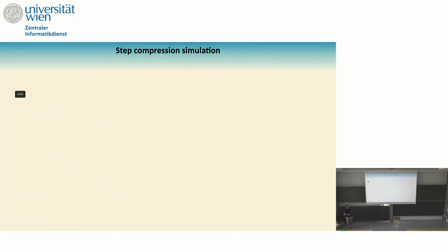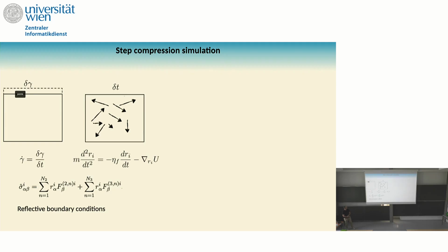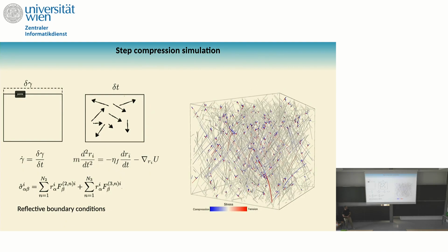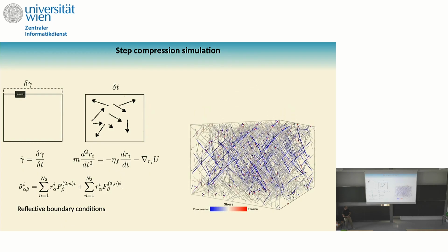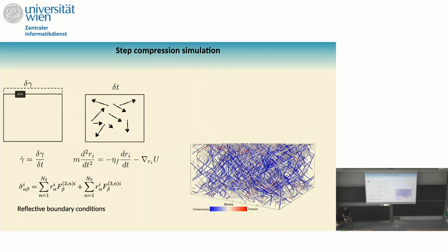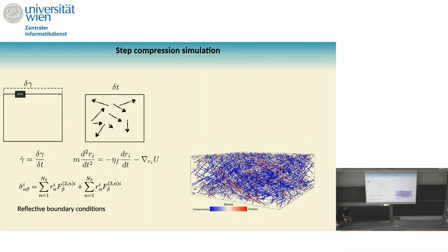Okay, how can we do the step compression? It is the same as the step shear. I will go very fast on that. We apply a step deformation, let the system relax with some dynamics, then measure the stresses. This is a video that shows you the compressive and the tensile stress when you are applying a deformation on your branched actin network, and you see that the system has more compressive stresses than tensile stress.